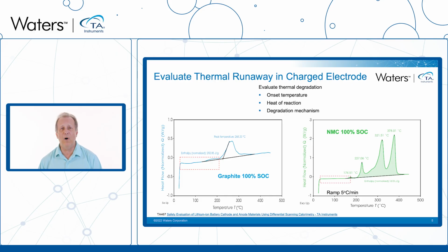So you can see from both of these, there is exothermic activity happening in both of them, but the energy difference and the character of the exotherms are quite different. On the graphite side, we have about 300 joules per gram of energy released. On the cathode side, though, we have about 1.6 kilojoules of energy released. And we see three separate exotherms there, dealing with three separate decomposition events.